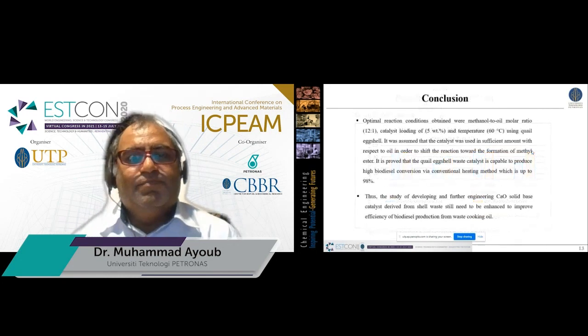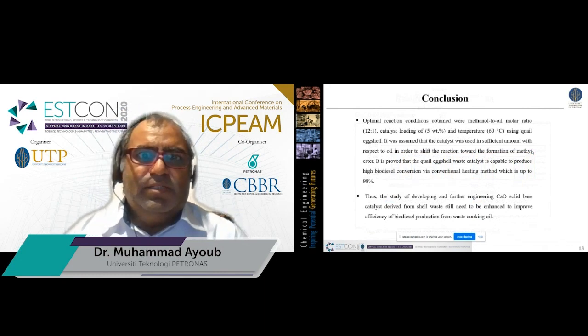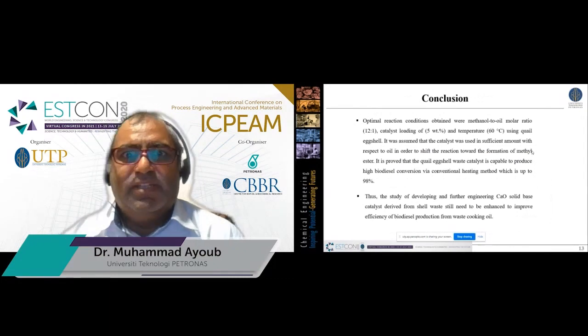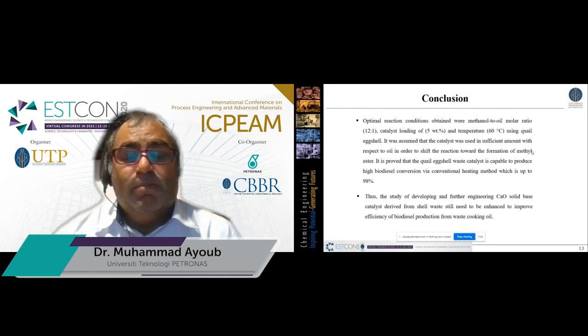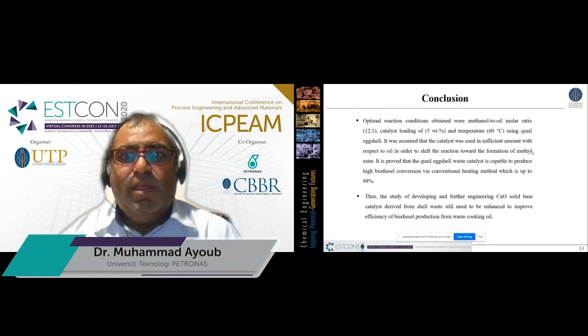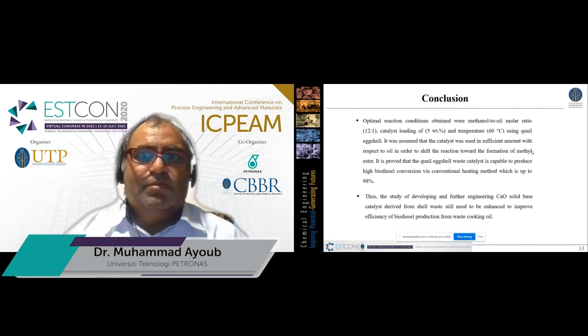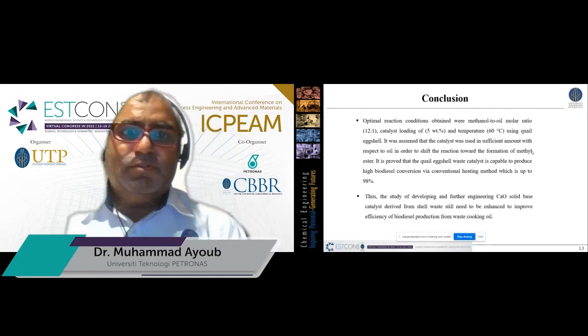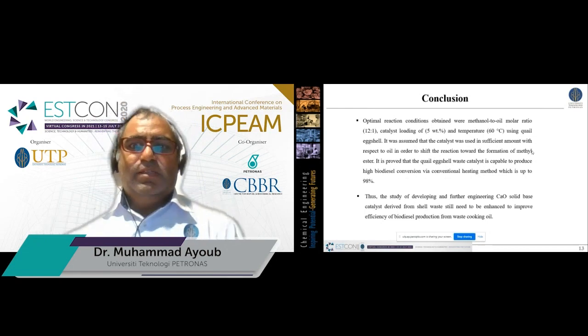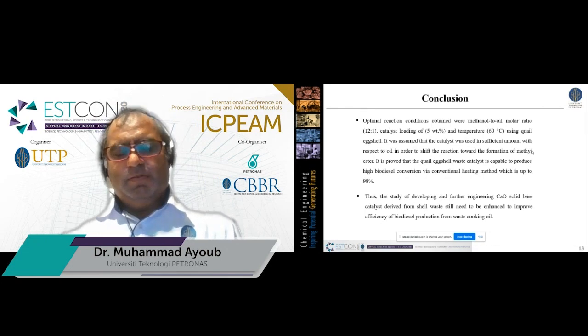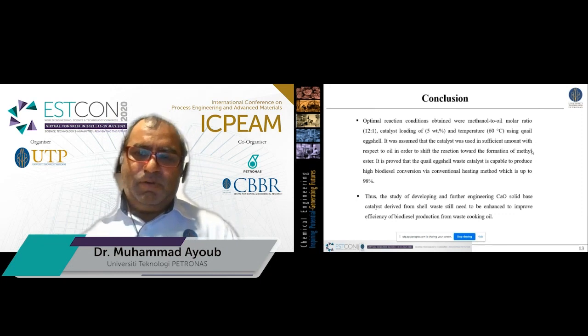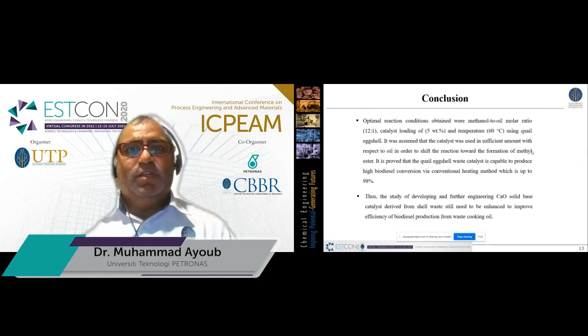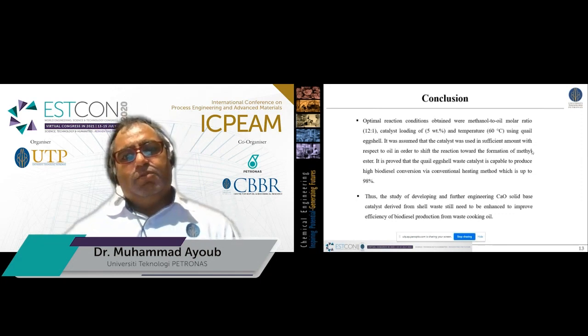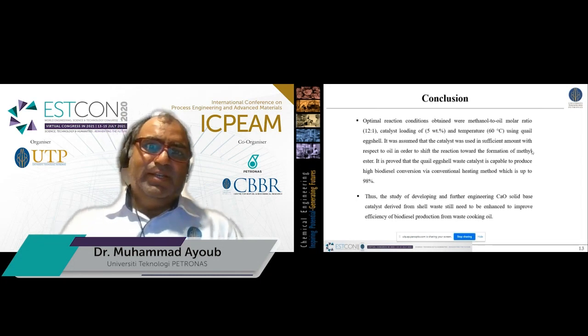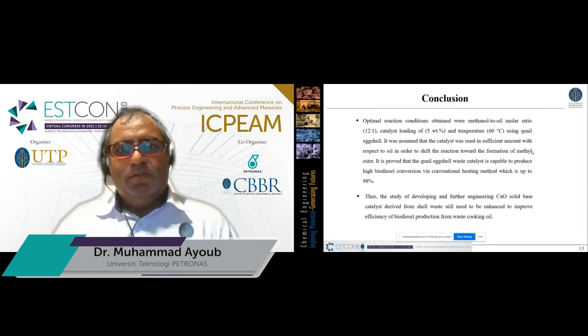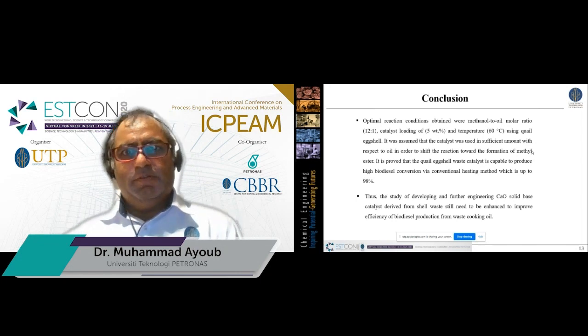Overall, we can say that the appropriate catalyst with eggshell and quail-based montmorillonite clay is successfully prepared, and different parameters were also measured with physical and characterization processes. We can say that it is successfully stable for different values. But one important thing is that the quail-based montmorillonite clay catalyst is more feasible, because it provides more than 90% yield of biodiesel production from waste cooking oil. For the future, we are working on changing different parameters, and on kinetics, to check whether it works for big scale or not. So that is the way forward.